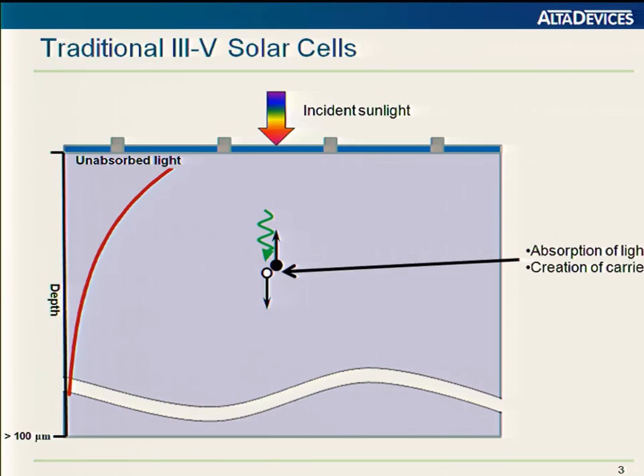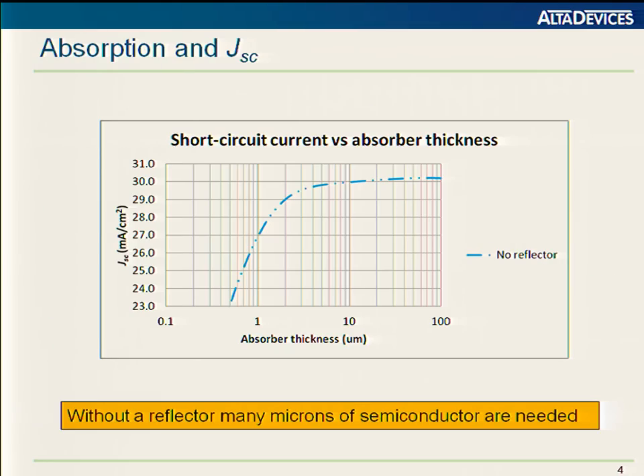If we consider a very simple model of absorption in a semiconductor from one pass of light, we get something like this as a curve of unabsorbed light as a function of depth. So we get exponential decay of the wavelengths with energy higher than the band gap energy. And as they're absorbed, they're generating electron-hole pairs that are hopefully collected by diffusion and then crossing the p-n junction to create current in an external circuit.